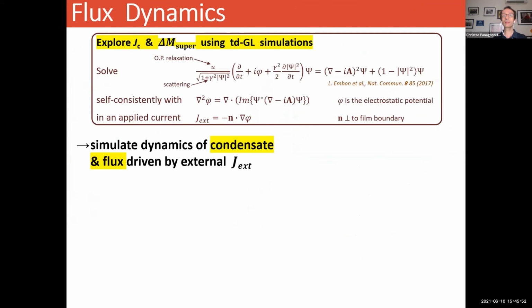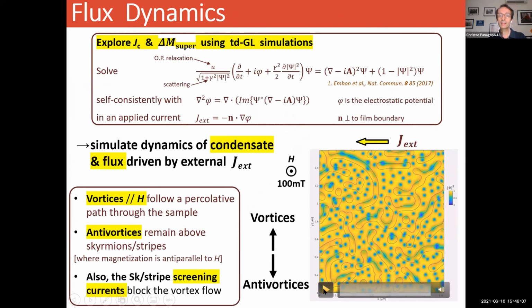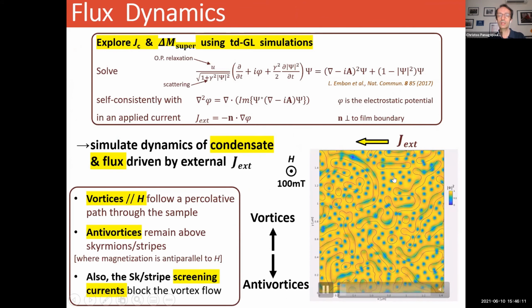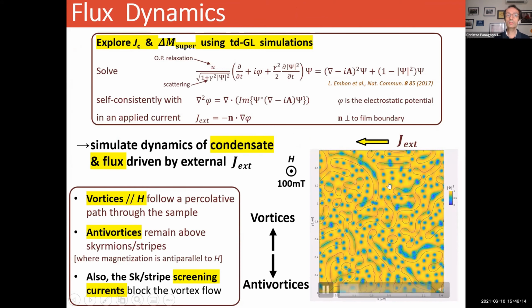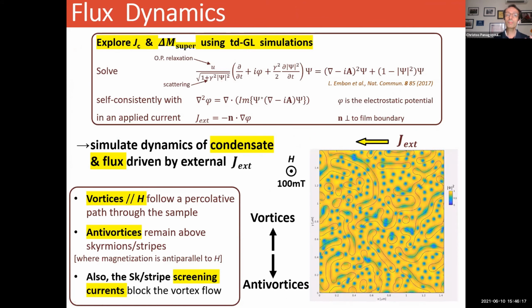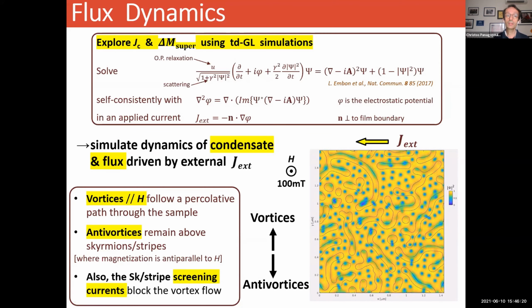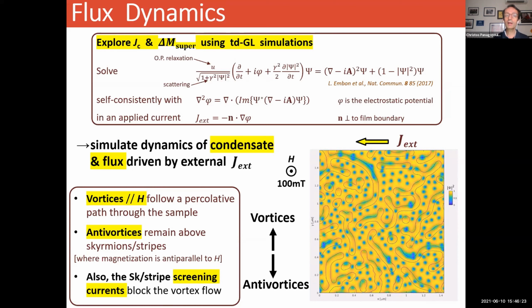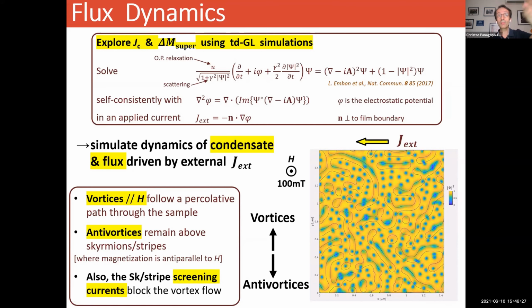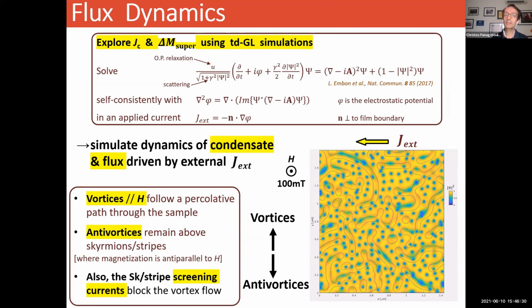And you can explore the critical current density and the changes in the magnetization of your superconductor using time-dependent Ginzburg-Landau simulations. By doing so, we can simulate the dynamics of the condensate and the flux driven by the external applied current density. What you see here from this plot is that the vortices, which are parallel to the magnetic field, follow a percolative path through the sample. You also have these antivortices remaining above the skyrmions or magnetic stripes or magnetic domain walls, where the magnetization is antiparallel to the applied field. And finally, the skyrmion stripe screening currents block the vortex flow.